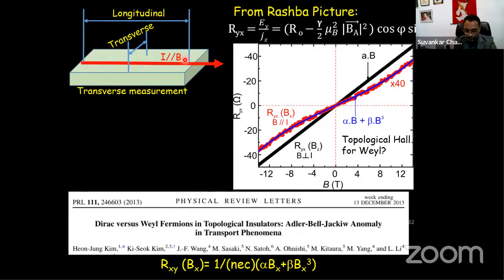But now we are confused, because let's think about this geometry where you apply the magnetic field along the direction of the current. If you apply the magnetic field along the direction of the current and want to measure the transverse voltage in a 2D material, you should not see any Hall because your V cross B term is 0. And from our Rashba picture, this was the expression for Rxy, which contains a cos phi sin phi term. So when phi is 0, you should not see any Hall effect.